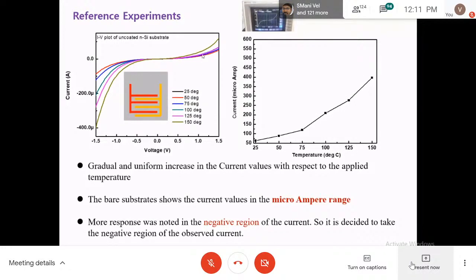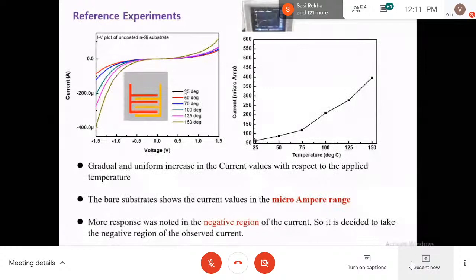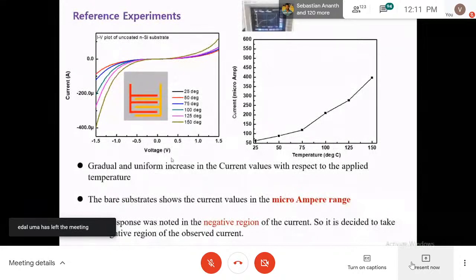The as-prepared sensor shows an electrical response with current in the microampere range. We checked how it responds at different temperatures from 25 degrees to 150 degrees. We can call this the temperature dependent electrical study. The response increases because usually a semiconductor shows an increment in response due to temperature. So first of all, we studied the electrical response from room temperature to high temperature. There is a gradual and uniform increase in the current values with respect to the applied temperature.